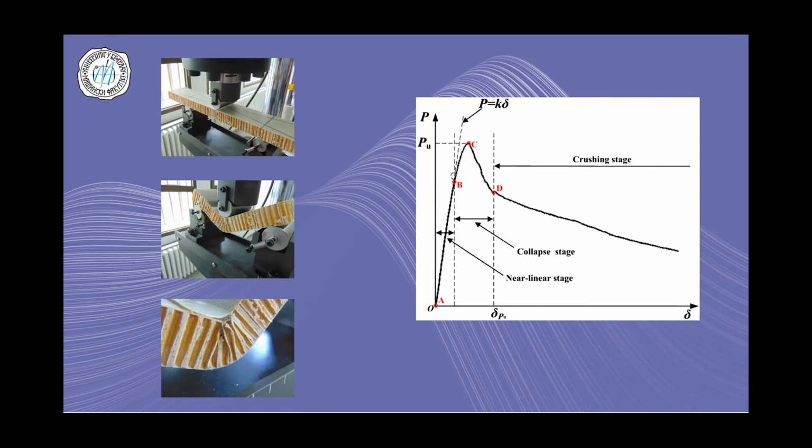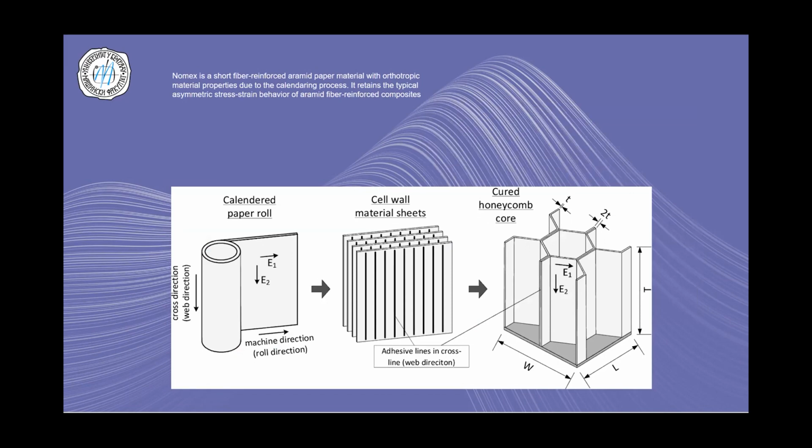Perhaps dealing with statics and in a linear domain, they're good because they're simple, they're efficient, they can be computed fast, and so on and so forth. But as soon as you try to switch to some other kind of non-linear analysis, dynamic analysis, or all kinds of fatigue analysis, this really won't do the work. So this is what we are trying to suggest, and we have experimented with this approach. To understand what I'm trying to explain in the next few slides, we really need to understand the manufacturing process of this honeycomb core. The starting point is actually paper, a really special kind of paper.